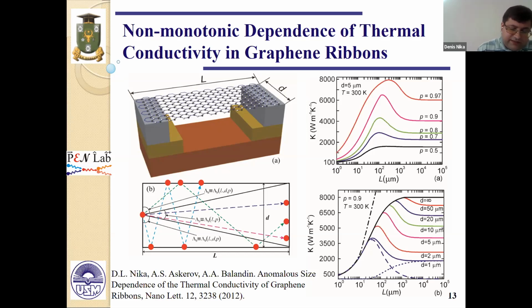I would like to note here that thermal conductivity is strongly affected by the flake shape and edge scattering. For example, for flakes with large widths or for flakes with strong edge phonon scattering, we obtain the conventional dependence of thermal conductivity without non-monotony. In the case of square or circular graphene flakes, we also obtained a monotonic dependence of thermal conductivity on the flake length. So non-monotonicity appeared only for rectangular graphene flakes.